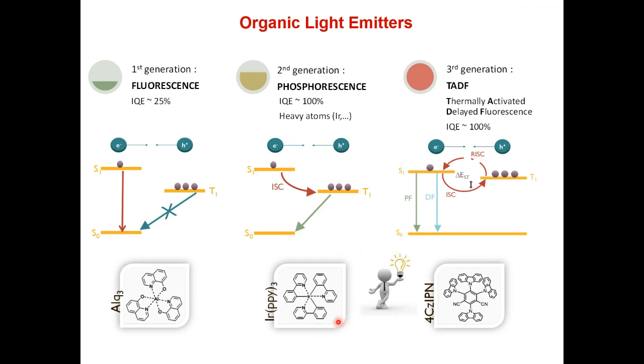What I didn't mention also is that if you want a very bright emission for all the materials here, you don't want to make a single layer made only with this material. Otherwise, there are many detrimental effects which are going to kill the fluorescence. So typically, those emitters are encapsulated in a matrix, and typically the matrix is 95% of the film, and those emitters are like 5%. So making color is not a big issue.